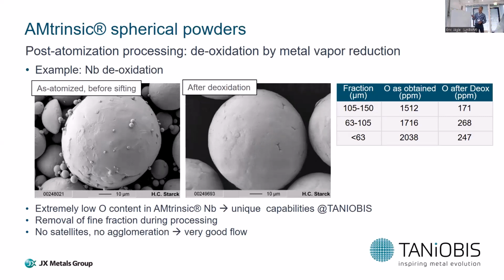You can see the effect of the deoxidation. Here you have the different fractions, so SLM, EBM, and LC. The oxygen contents of this niobium after atomization, and here the values after deoxidation. And accordingly, this deoxidation has a tremendous effect. We can even go lower, but then the particles get very difficult to handle because of pyrophoricity when exposed to air.